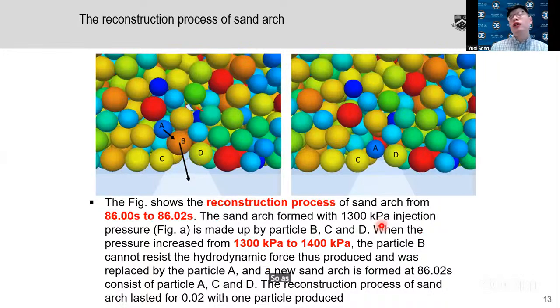As I mentioned, it's very important to know the collapse and reconstruction of a sand arch. Here I have captured a reconstruction process of a sand arch in the simulation, going from 86.0 seconds to 86.02 seconds. So this reconstruction process lasts only 0.02 seconds, a very short time. When I increase the drawdown pressure from 1300 to 1400, I see this phenomenon. Particle B is kicked, or flushed away by the fluid, and its place is replaced by particle A. In the left figure, CBD is the previous sand arch, and this sand arch collapsed, and a new sand arch is formed by particles C, A, D.